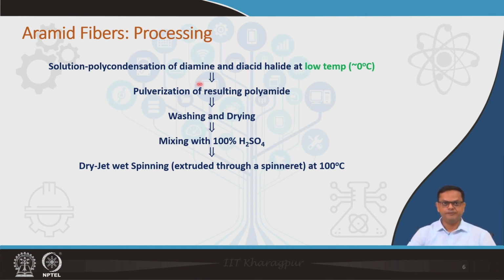After getting the aramide, that gets pulverized, that means you make it in powder form, and then you go for washing and drying, and then a very important step is mixing with concentrated, 100% H2SO4, and I will discuss this particular step in detail. Once that is done, then you go for a spinning method, which I have discussed earlier, dry jet wet spinning method at 100 degrees Celsius. Now, dry jet wet spinning method is basically a combination of dry spinning and wet spinning. I will discuss this again as we move on.